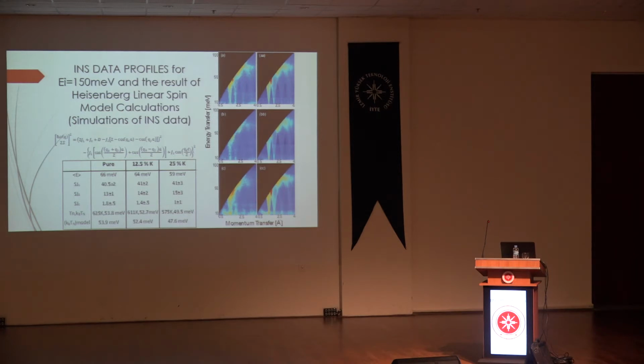After the preliminary fits, when I get the best values of chi-squares for the preliminary, I decided to go like 30,000, sometimes 50,000 Q values, and recalculate the best like 10, 15 chi-square values, and get more precise values of Monte Carlo. As you know, Monte Carlo technique is a random selecting abscissa technique to calculate the Y values, depending on the abscissa values. If you have a limited number of Monte Carlo seeds, you will have a big difference in each iteration. So I need to get those differences as small as possible by introducing so many, like 30,000, sometimes 50,000 Q values. This is the data, that is my analysis.